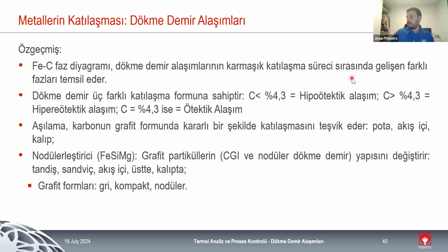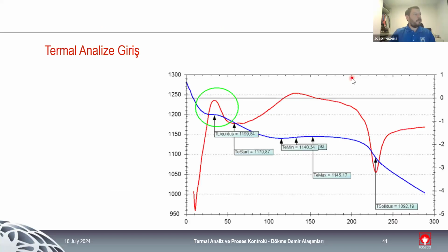And a small resume. So the phase diagram is important for us to understand the complex solidification process of cast iron and to identify the type of solidification that we are going to have: eutectic, hypoeutectic, or hypereutectic. The main goal of the inoculation step is to promote the stable solidification of carbon and to limit the amount of carbides that we are going to have in the cast. And the main role of the magnesium treatment is to change the shape of graphite from gray to compact to nodular based on the amount of magnesium that they are going to have.